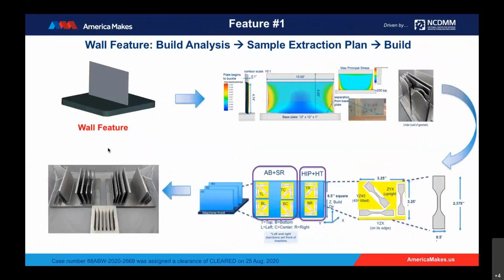So from the basic part of the feature, like I mentioned, we start with this basic feature, which is the thin vertical walls. We start with the dimension of the wall of choice. So what we looked at is the wall of 6-inch tall, 10-inch long type of dimensions, and then the wall thickness governed by the beam width with the overlapping beads for the single or the triple build strategies. For the C+H or the contour plus hatch type of build strategies, we ended up having similar wall thicknesses in terms of our targets.